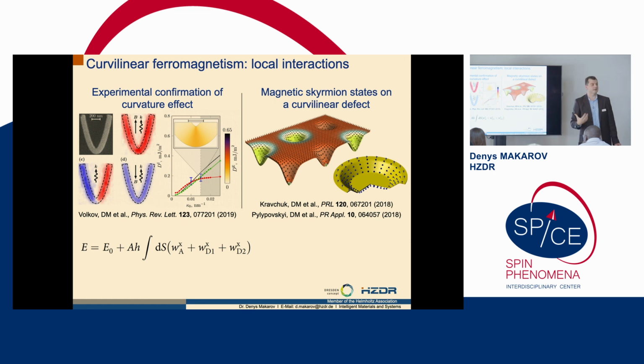So this is a translation of some complex effects to a very simple language. If you know about this Dzyaloshinskii-Moriya interaction, you can tell, okay, if I have such a system, I will necessarily have space inversion broken here, right? And that means that I will have chiral effects by default there. Therefore, these domain walls will be of a certain chirality. Okay, that's it. So you will have skyrmion bubbles, if you want, defined by geometry.